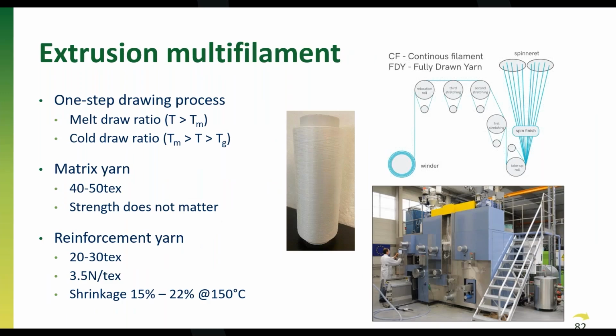So first of all, the 1-step drawing. On the right-hand side, you can see a schematic here where you have the spinnerets, the yarns, so the molten material comes out of the holes and is being stretched first time in the melt, so melt draw ratio we call this, to the take-up roll. In this case, in the one-step drawing process, the speed is not that high at our pilot scale equipment, I must say. We're at 300 to 500 meters a minute.